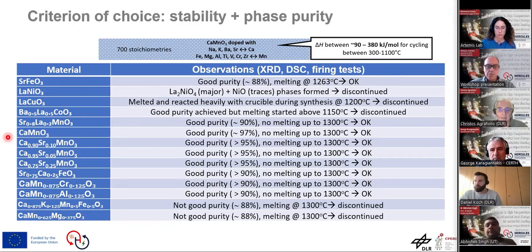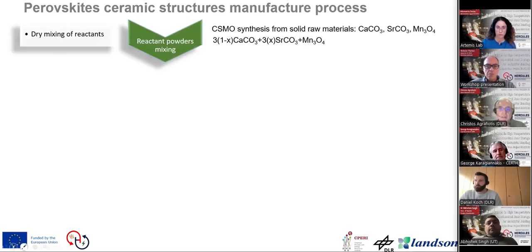Fine, then we go, okay, now we selected also a narrower family of cations, and if we click now into the next slide, we have the issue of how we're going to build and make these porous ceramics that we saw before. For instance, let's say that we start with a mixture that contains calcium, strontium, and manganese. We start from the precursors. These are powders. In our case, we use carbonates and oxides.